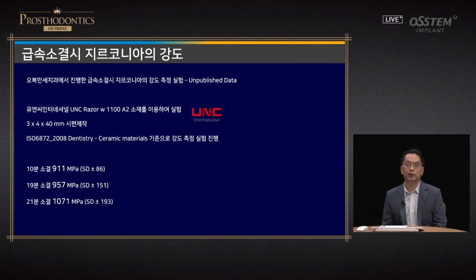Upon 10 minutes of sintering, 911 megapascal, and 19 minutes of sintering, 957 megapascal. In 21 minutes, 1071 megapascal was measured. However, it's difficult to measure yourself. For your information, when you sinter zirconia, if it shows a certain level of translucency, it means that the zirconia has reached a certain density, and therefore it has sufficient strength.